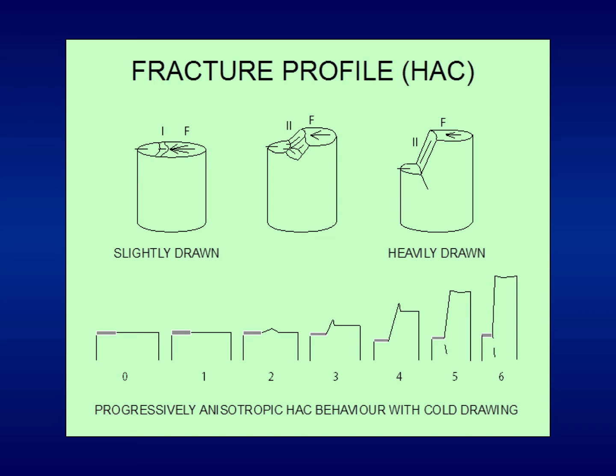For 0, 1, 2 degrees of cold drawing, and for intermediate degree of drawing, there is a slow propagation by mode 2, mixed mode, in hydrogen-assisted cracking subcritical conditions. In the most heavily drawn steel, after fatigue pre-cracking, there is a sudden deflection angle of almost 80-90 degrees and fracture propagation in almost perpendicular direction to the initial one in mode 1 by fatigue. There is a strong component of mode 2 in this mixed mode and anisotropic hydrogen-assisted cracking